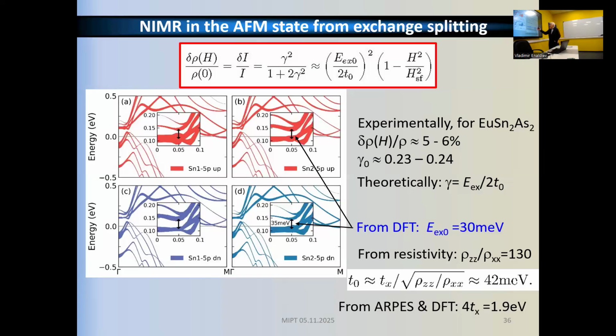Perpendicular. Now, everywhere, roughly, it has an order of 30 meV, but you understand that this is only a qualitative estimate. What about T naught? T naught is very hard to calculate numerically, but we have some prompts from the experiments. First, we have the anisotropy of the resistivity, which is a factor of 100. This is a very layered material, a van der Waals material, so it's well conducting in planes and has 100 times less conductivity across the layers.